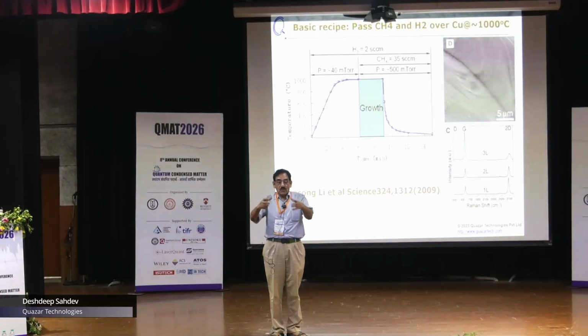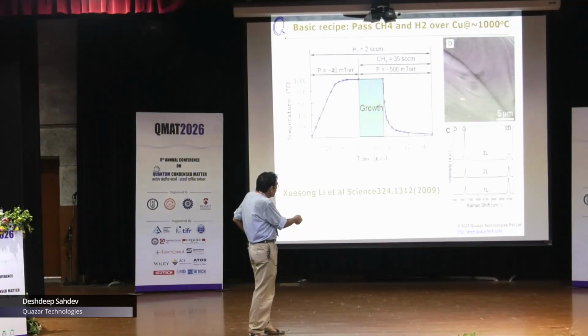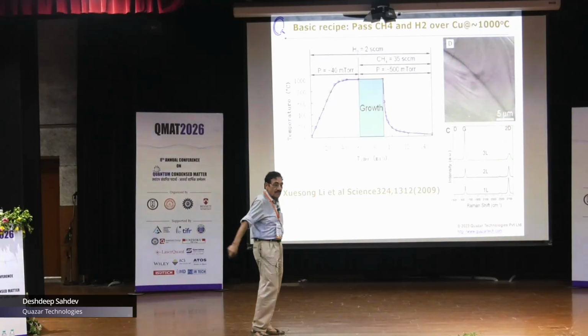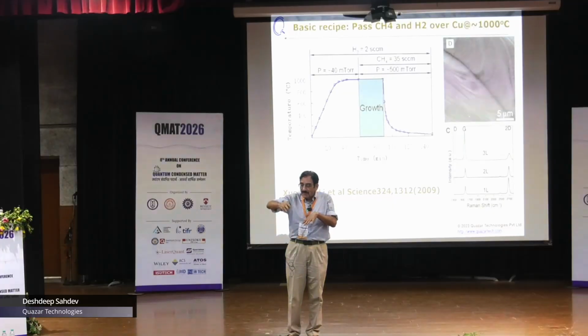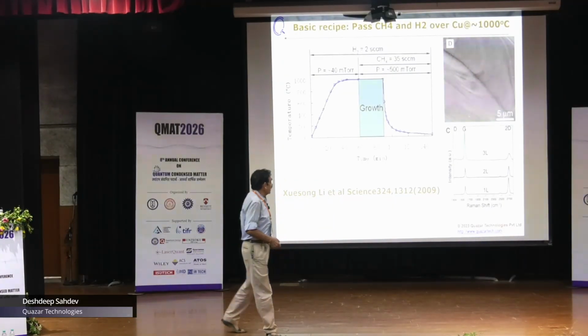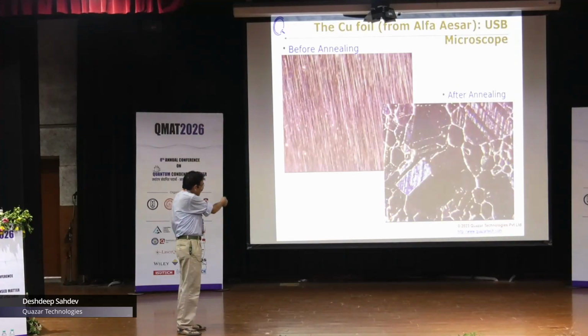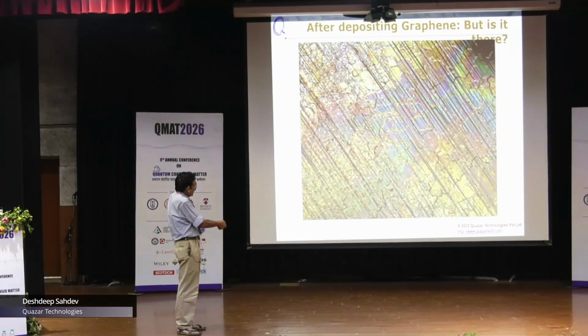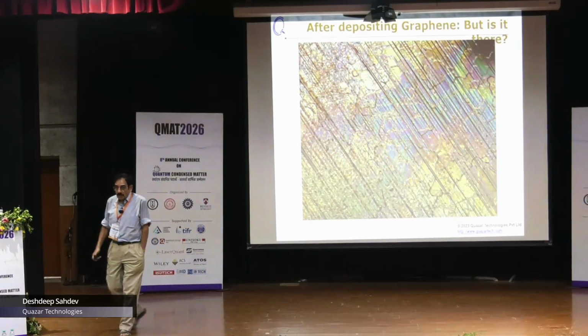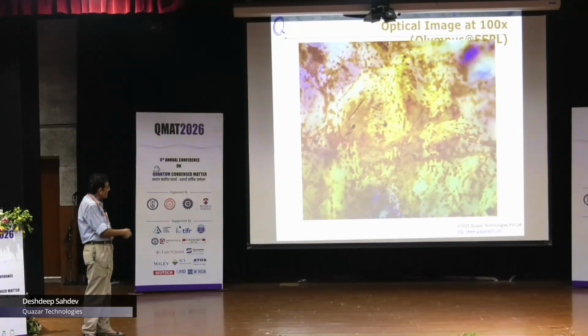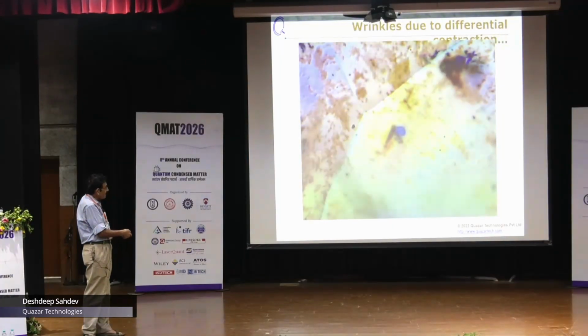And when you cool it down, the copper shrinks, and the graphene doesn't shrink as much. So you get these wrinkles on it, and it's because of the wrinkles that you actually start seeing the graphene. That's how it becomes a little easier to see. So we just did that with copper here. We annealed it, and then we ran this. There's supposed to be graphene on top of it. Almost impossible to see, but you keep on magnifying it, and now here you start seeing the wrinkles. So this shows you that graphene has formed, and here you see the wrinkles even more clearly.